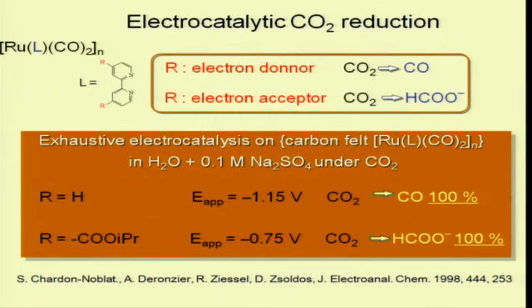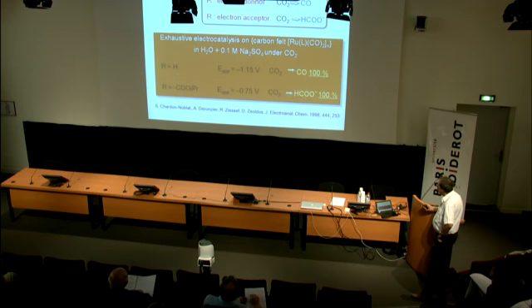And another interesting thing is that we were able to tune the selectivity of the reaction by introducing an electron acceptor on the bipyridine ligand. You change totally the selectivity. In this case, you get the formate instead of the CO.